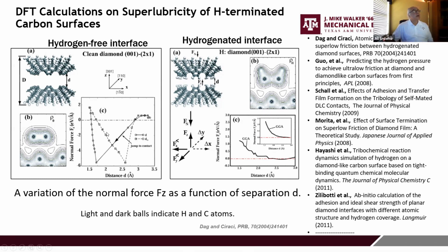But if the surfaces at the interface are fully hydrogen terminated, and you do the same thing, bringing these surfaces closer to one another, at a distance of about less than 2.5 angstroms, these surfaces would actually start developing repulsive forces, as shown at the bottom.